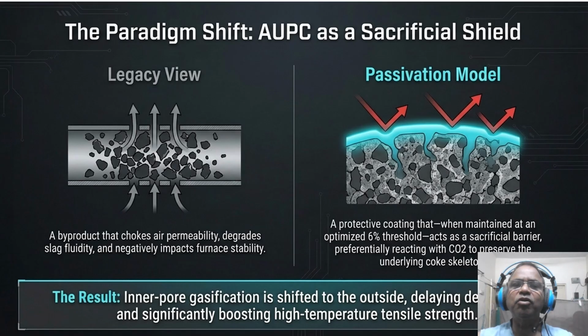When we maintain that optimized 6% threshold, the AUPC acts as a sacrificial shield. It preferentially reacts with CO2 so that the coke doesn't have to. We are literally shifting the inner pore gasification, which destroys coke from the inside out, to the outside surface of the AUPC. This delays degradation and quite frankly is the only reason we see such a massive boost in high temperature tensile strength.